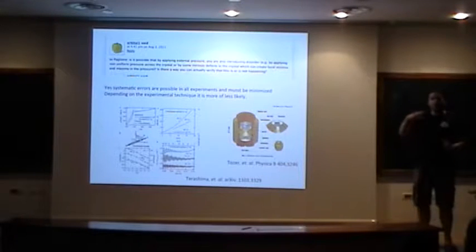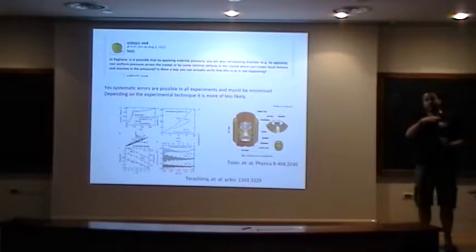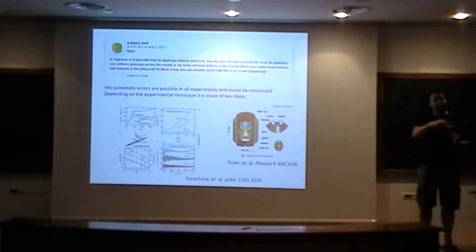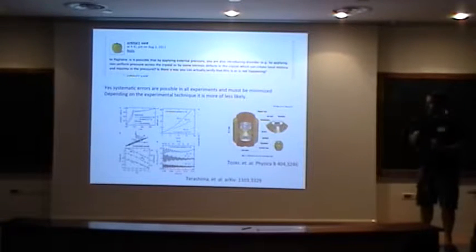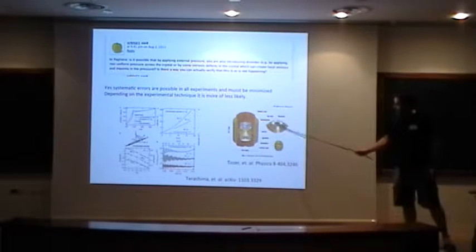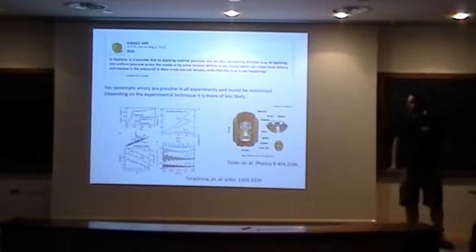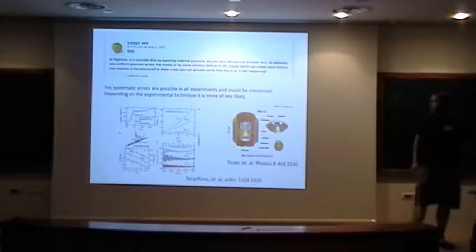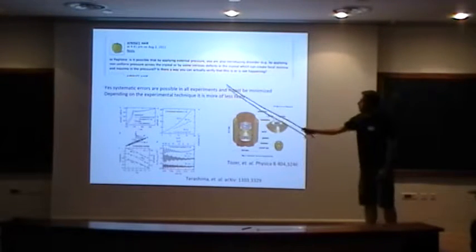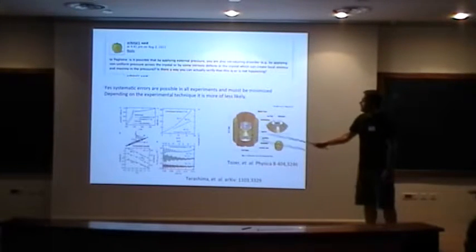So it's not like you just have a uniaxial strain that you press on one side of the sample, where it is actually possible, if you're not perfectly aligned and the surfaces are not perfectly parallel, that you introduce some defects in the sample. But they have a uniform pressure on the sample, which reduces this effect. And, is there a way you can actually verify that this is not happening?